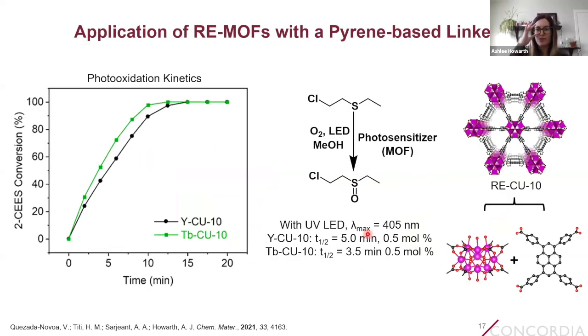And so how does Victor do this reaction then? So he takes the mustard gas simulant, the 2-chloroethyl ethyl sulfide, he puts it in methanol solvent with the MOF, which is a solid powder and remains a solid powder throughout the whole reaction. He purges the mixture with oxygen to make sure we have an oxygen-saturated environment. And then he irradiates that mixture with a UV LED that excites directly into the pyrene photosensitizers.